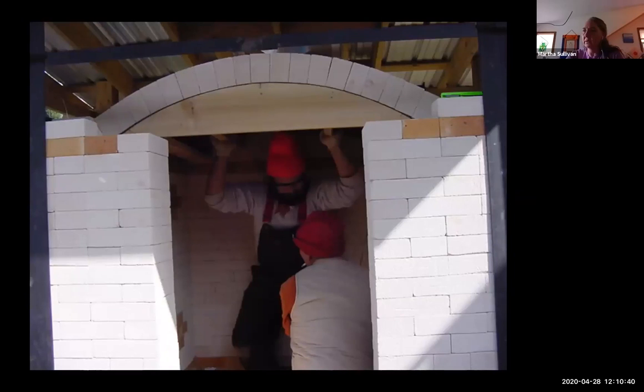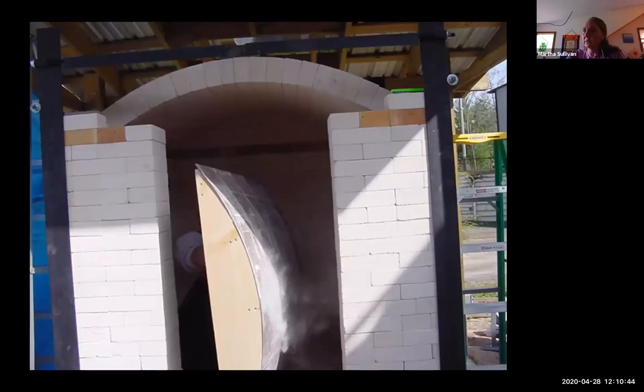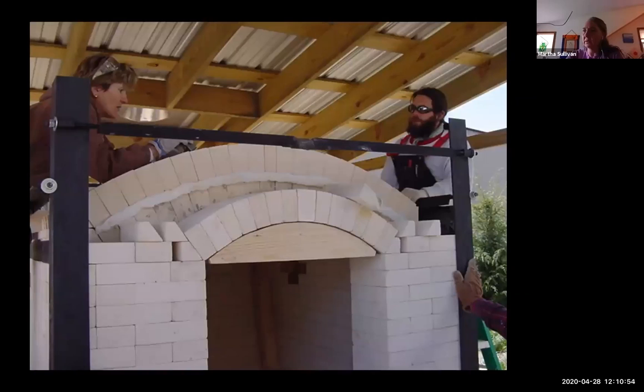And when the arch was totally in, we were able to lift out that wooden piece, and then the arch stays in place because of the way that the angle iron is cinched around the kiln. We put on a layer of fiber and then a second layer of bricks. So the kiln in any one place is 8 or 9 inches thick to reflect the heat back in. And there you can see that there was a separate wooden form made just for the door arch. So pulling the arch into the wall, making it a little bit smaller.